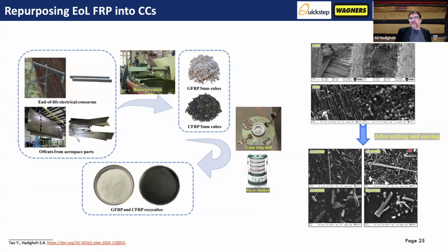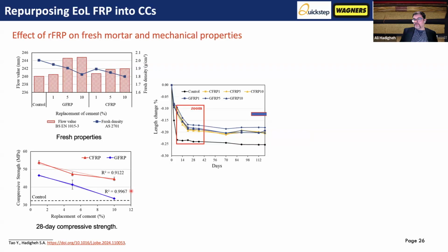But to start, we worked with two different companies. One of them, as I said, was active in the aerospace industry, airplane components, and another one was in construction, and they were producing cross arms out of GFRP. So what we did, we downsized these GFRP and CFRP components, we pulverized them, converted them to powders, and then we replaced cement with these CFRP and GFRP recycled material. And consistently, I think a lot of people have done this kind of research, the properties of these materials were better than the control without any waste materials. The performance was better than the control.